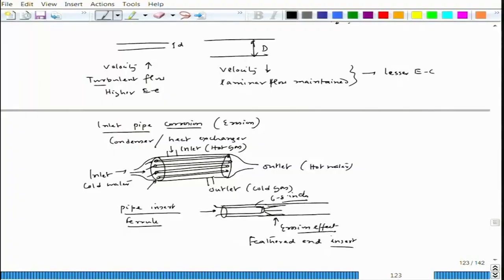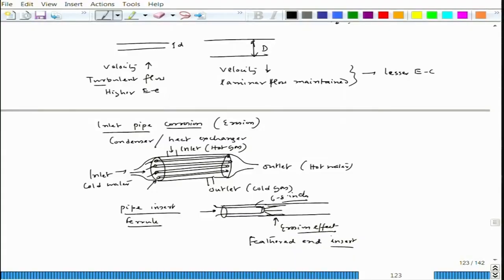Now removal of a 6 inch or 8 inch ferrule would be much easier, but the main heat exchanger pipe would be close to 20 to 30 to 40 feet in length. In that case, if we find an erosion corrosion problem at the inlet of the main pipe, the entire piping should be removed, and that will be a very costly affair and it will stop the plant operation. So it is better to use a ferrule, so that the 6 inch ferrule can be removed quickly and then the heat exchange process can be restarted immediately. So that is one such instance of design where erosion corrosion can be avoided to a great extent using a pipe insert or ferrule.